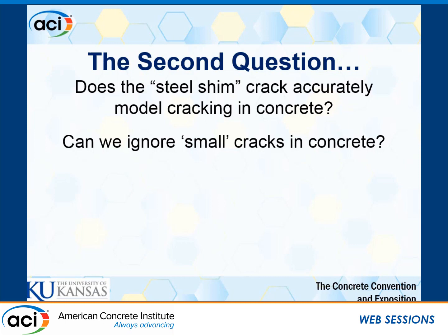If we're out there on a bridge deck survey trying to evaluate the cracking performance of a deck, intuitively, yes, if you can look outside your car window and see cracks from there, that's pretty bad. But how bad is it really if you have to get all the way down on your hands and knees with a magnifying glass to see a 1 mil or even a narrower crack there? So can we ignore those small cracks? Or even on a more philosophical level, when is a crack really a crack?